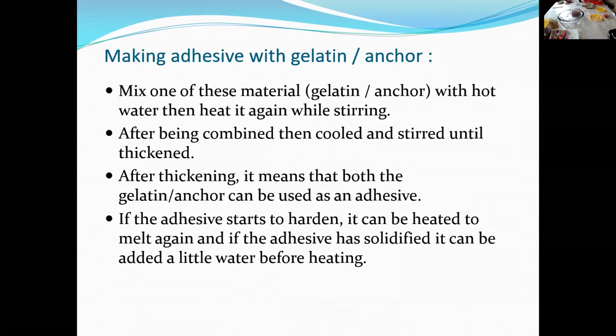We mix the material of gelatin anchor with hot water and then stir it as we heat it up. After being combined, it is cooled and then stirred again till it thickened. After it's thickened, it means that the material is ready to be used as an adhesive. If the adhesive starts to harden in the container, it can be reheated to melt it again. We will try to show you the procedure.